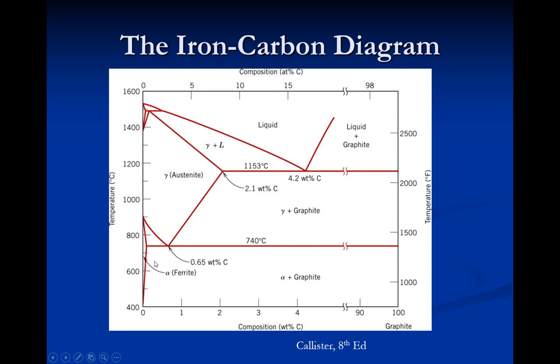The other point that's interesting, and this is the key point for defining the whole family of iron-carbon alloys that we call steel, is this transformation from austenite to ferrite, and we usually say cementite, a two-phase solid region here. So single phase, this is FCC, or face-centered cubic iron, which has a very high solubility of carbon.